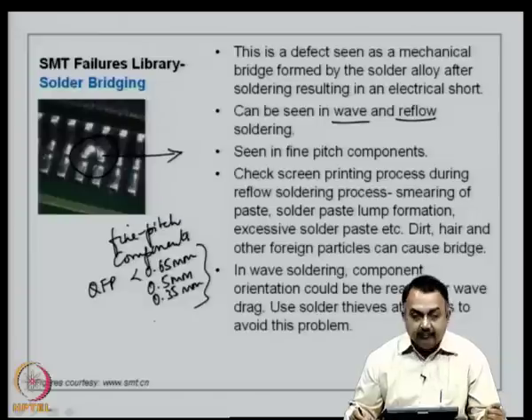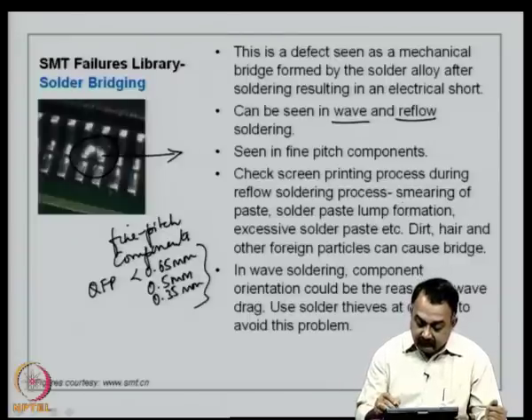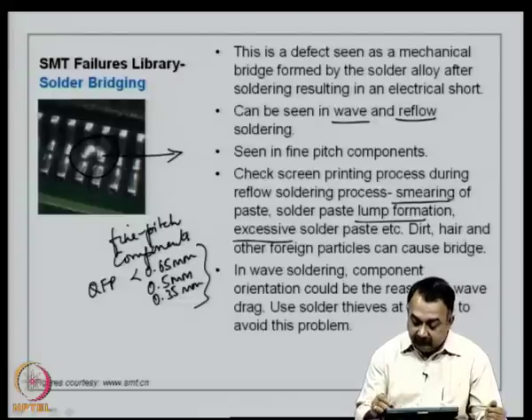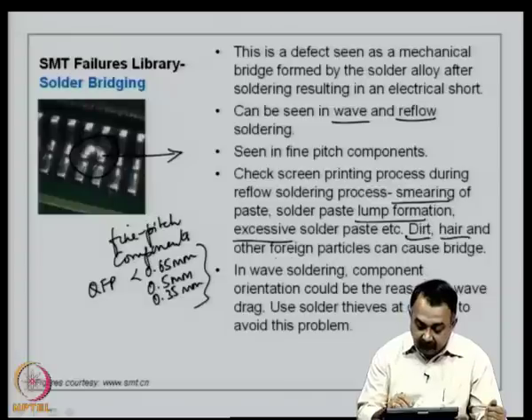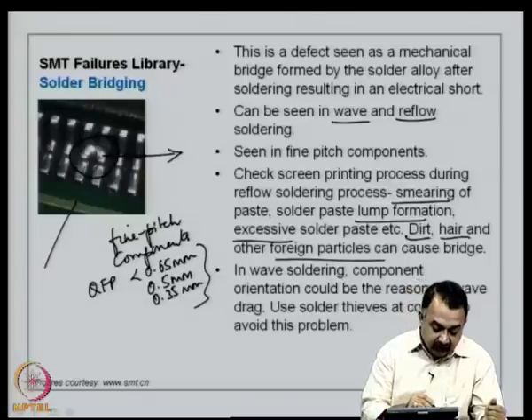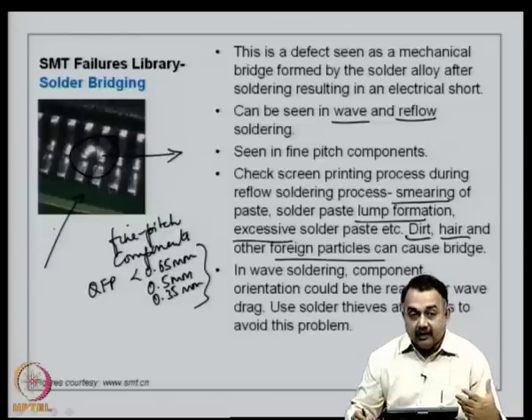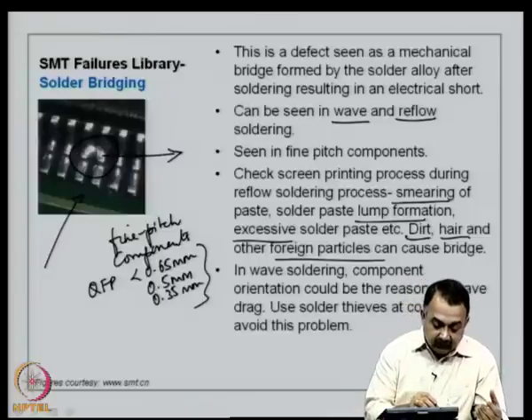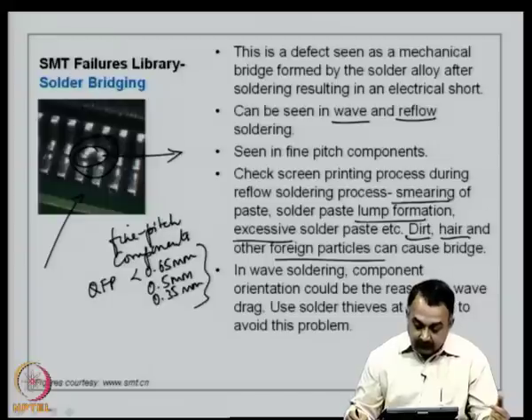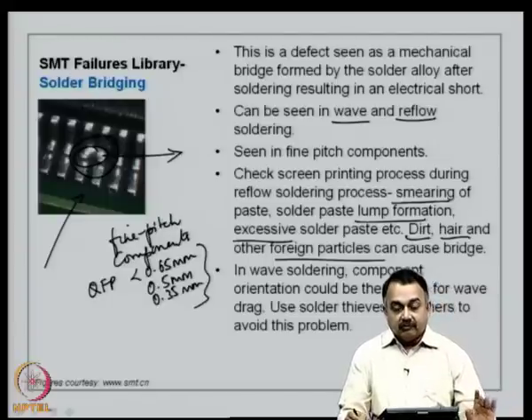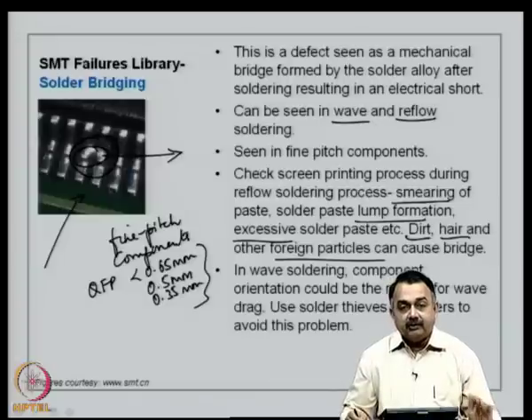Now, how do you rectify this? Check screen printing process during reflow soldering process. That is, if the solder paste is smearing, if there is a lump formation, excessive solder paste, if there are contaminants like dirt, hair or other foreign particles attached onto the PCB and if you have not taken care of during placement of the component, then there is a very good chance that they will attach themselves to the solder paste material, and that could be one of the reasons for the formation of the solder bridge.